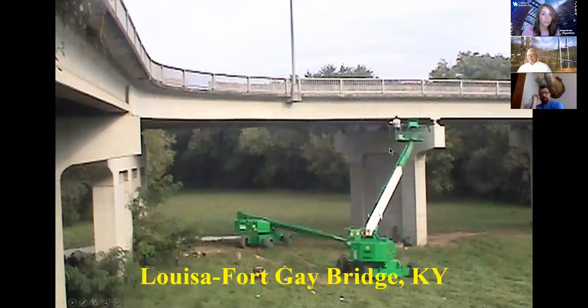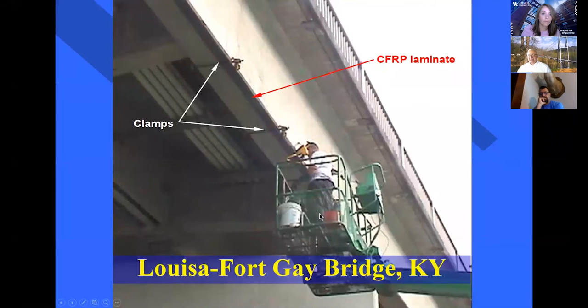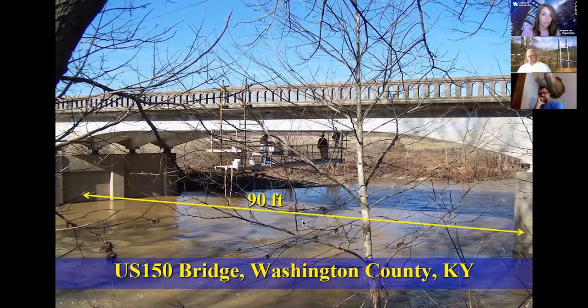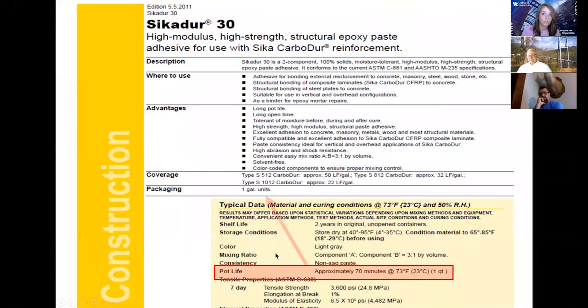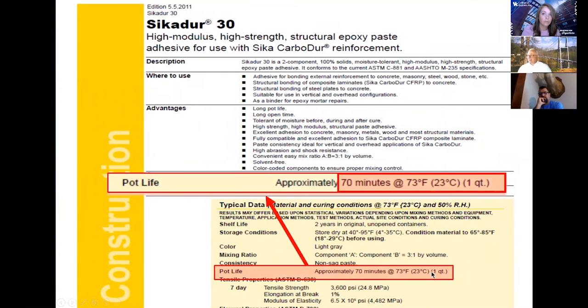For example, for the Louisa Fort Gay, it takes quite a bit of time to put that laminate on the soffit of the beam. And the problem we have is that when you are applying these materials, the resin that we use has a pot life of 70 minutes. Actually, if it takes you 20 minutes from the time you mix the resin to apply the laminate, you lose about 40% of the capacity. So for this reason, we don't really use it anymore, because many times it takes us at least 30 minutes to apply the material on a bridge.